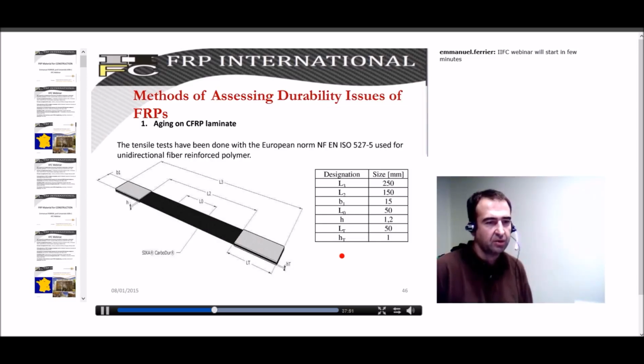For testing material in our field in construction, it's quite well identified now. Generally, everybody uses this ISO norm for the tensile test. There is also an ASTM standard, which is a little bit different in its sizing, but it's quite similar in principle. Coupons are made of unidirectional material, and then it is tested directly in tension.